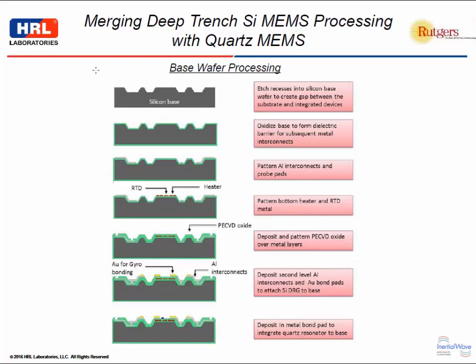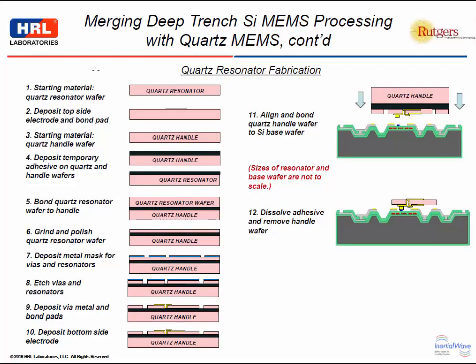This was sort of one of our Achilles heels during the process. The via interconnect resistance actually turned out to be higher than we expected between the two layers of aluminum. And we need to do a better job of keeping that interconnect resistance at the via down, possibly by doing some in-situ plasma or sputter cleaning during the final aluminum deposition. But I'll say a little bit more about that in a few minutes. Then we applied gold pads for bonding the silicon device. This is very similar to the way we processed the silicon DRG in the past. And then what we added was an indium dot, or a couple of indium dots, right here in the middle for the quartz bonding.